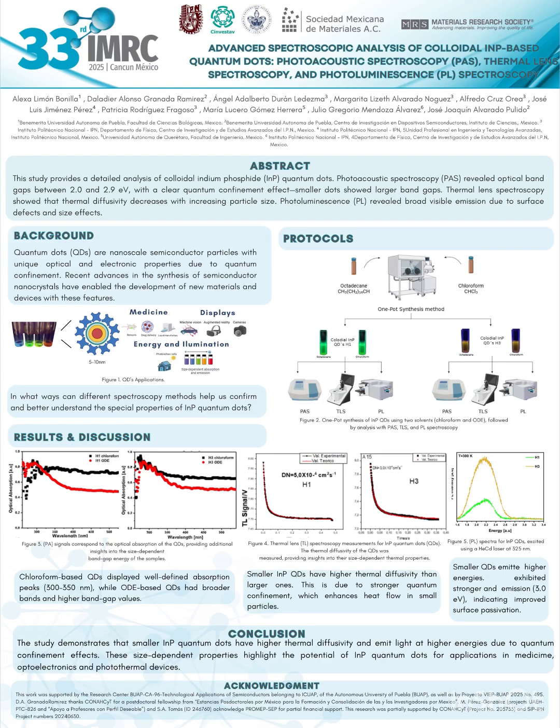In contrast, H3 showed the most intense photoluminescence signal among all the samples, with a sharp emission peak around 2 electron volts. The high intensity of this sample, H3, suggests highly efficient radiative recombination, which means that excited carriers recombine directly by emitting photons efficiently with minimal energy loss. When non-radiative processes are present, excited carriers lose energy through several intermediate steps before they can emit a photon, making photoluminescence slower and less efficient.